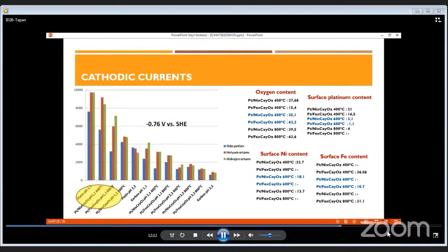If we go to more negative potentials, at -0.76 volts versus the standard hydrogen electrode, we see that pH becomes the most dominant parameter together with hydrogen purging.